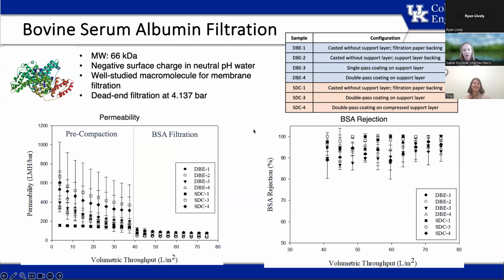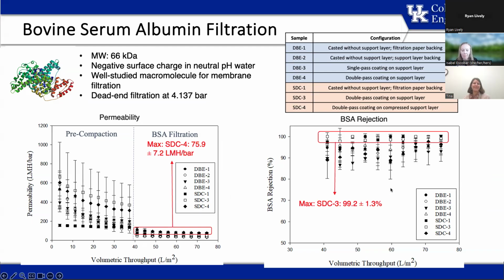We did permeability using a couple of different solutions. We did a BSA solution because BSA, again, is very well known. There's a lot of data for BSA using polysulfone membranes. What we found is that we started with a pre-compaction, and that pre-compaction was more needed for those membranes made at the scale of the Dr. blade. When they were made with the slot die coater, that pure water filtration pre-compaction did not show as significant of a drop as it did with the Dr. blade. However, when we started the BSA filtration under pressure, all of them performed at approximately the same permeability, and all of them within error had high BSA rejection, with the slot die coating membrane that was pre-treated with just the spray coating showing the highest BSA rejection.